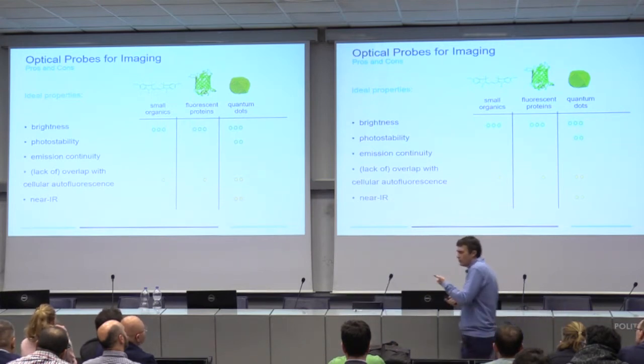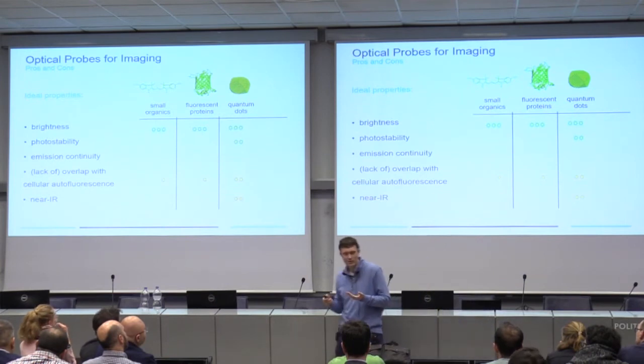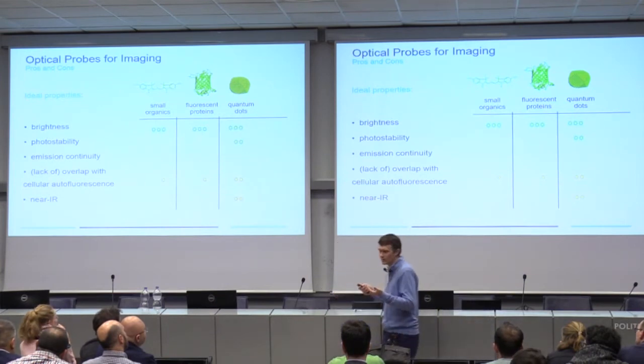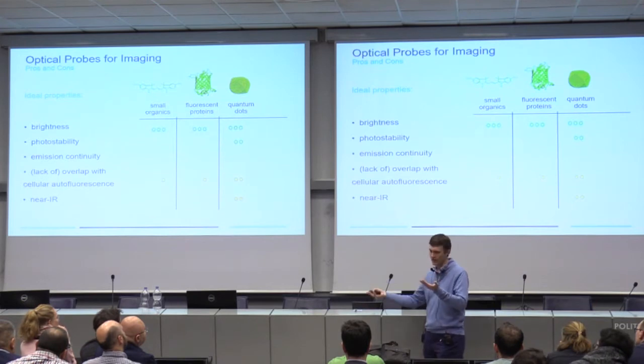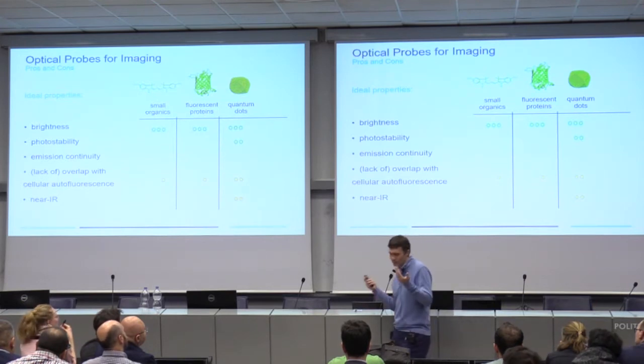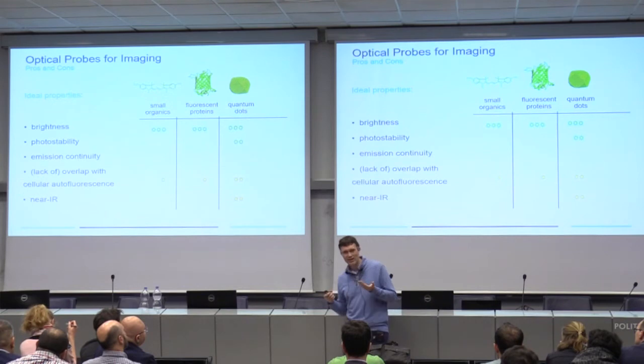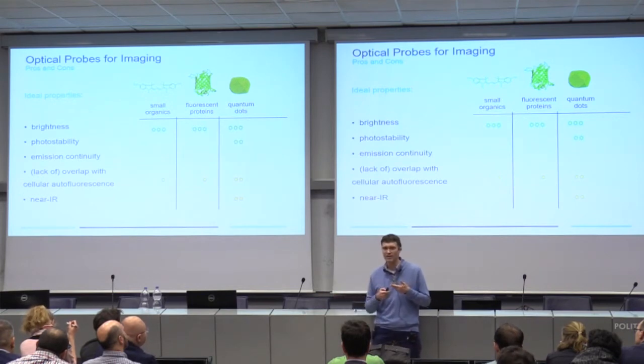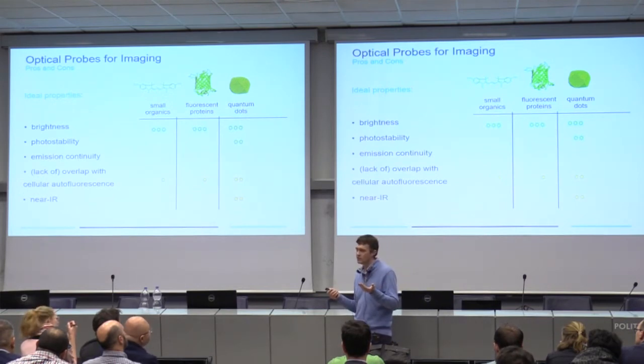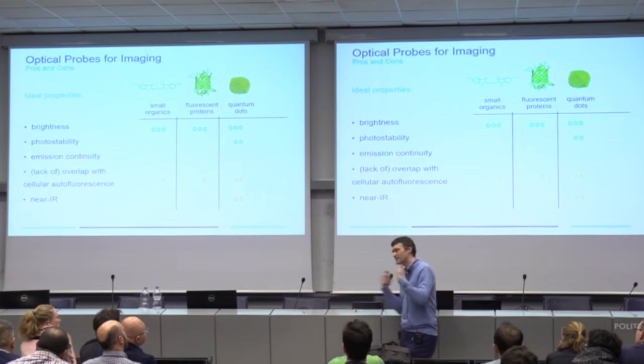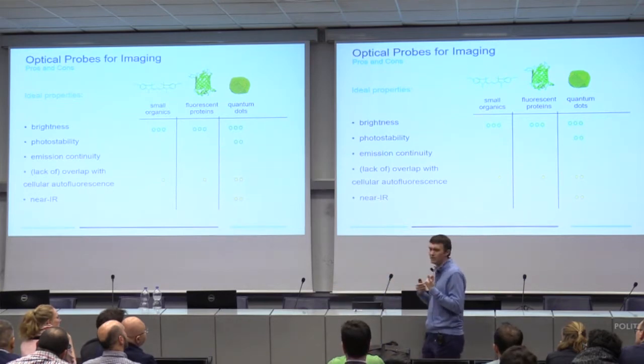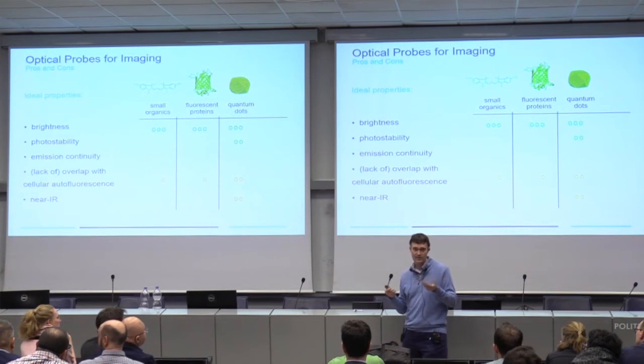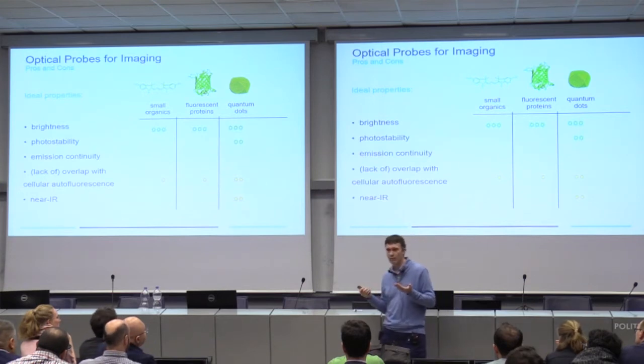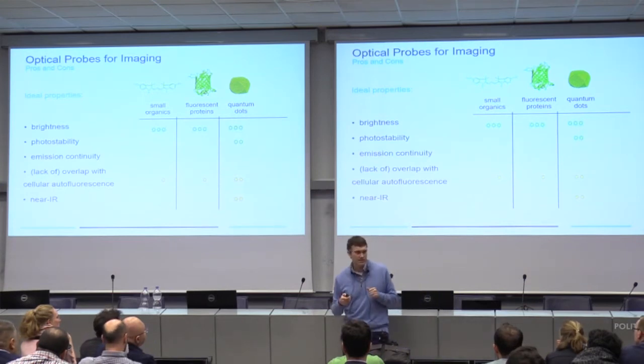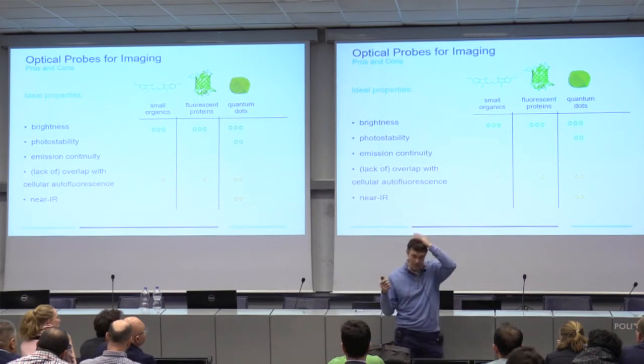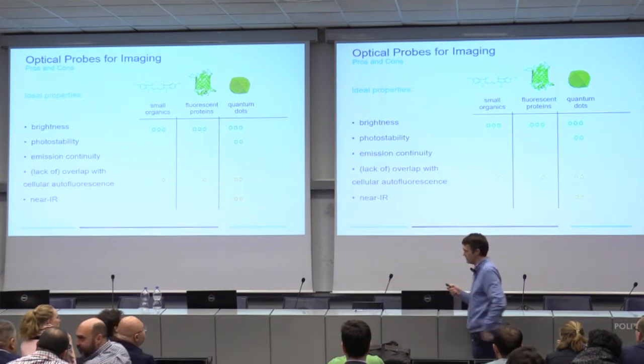The other issue is that all of these luminescent particles, right, are so-called Stokes particles. You excite at one wavelength and they emit at a lower energy. And that makes sense, according to the conservation of energy, but it's also a problem because it turns out that lots of things, say in biology, also fluoresce. And so this means that the luminescence that comes out of your probe also overlaps with this cellular autofluorescence. And this background is a huge, huge problem for most imaging studies and biological studies. Actually, not just in biology, in most imaging studies, autofluorescence is an issue.